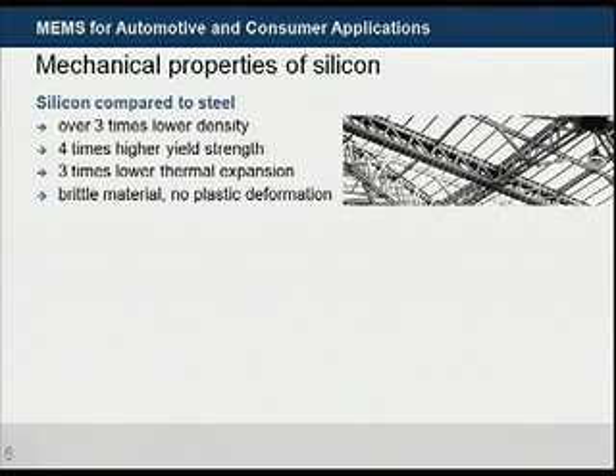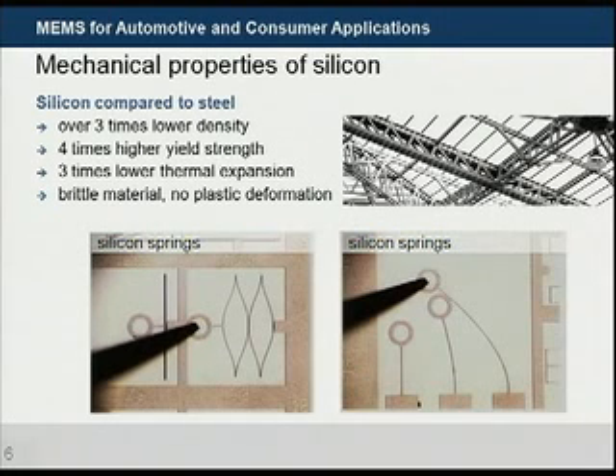Why use silicon for sensors? Besides the excellent electronic properties, silicon has also very good mechanical properties. Silicon is 3 times lower in density, but it has 4 times higher yield strength. Silicon is 3 times lower in thermal expansion. It's a single crystal material, and therefore it's brittle. We have no plastic deformation. On the bottom, you see some structures made out of silicon. These have the rings, so with the tweezers they can be deflected, and you see what kind of big deflection movement we can actually do on these silicon structures.